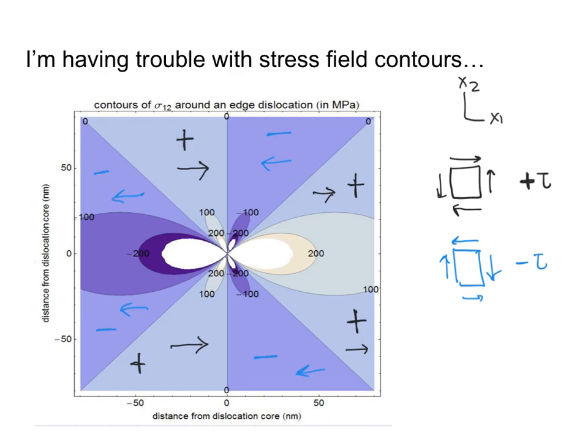As we talked about in class, inside this x equals y space, the dislocations move together to line up underneath the original dislocation that's sitting at the origin, and then in these side sections over here, if a dislocation is sitting there, it's going to be repelled away from the original dislocation.